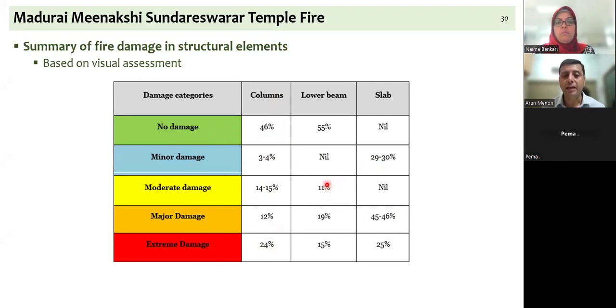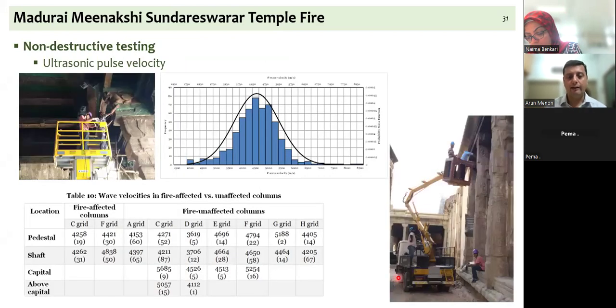If you look at the beams, we are at about 45% of the beams that are in moderate to extreme damage. If you look at the slabs, we are at about 70% of the slabs that are in moderate to extreme damage condition. So this gave us an idea from only visual inspections that about 50% of this structure is in really bad condition and may not be in a position to be reused. We then carried out multiple tests.